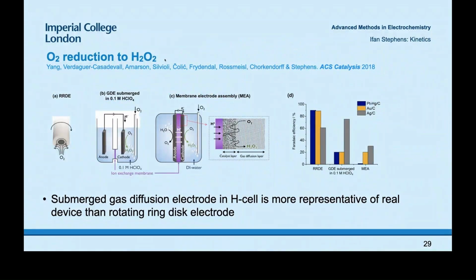So we found, for example, some very interesting catalysts for oxygen reduction to hydrogen peroxide, using, for example, platinum mercury catalyst. We found gold worked pretty well. And then when we actually tested it in a membrane electrode assembly, what we found is the catalysts that worked most well, like the platinum mercury, worked really badly in an actual real device.